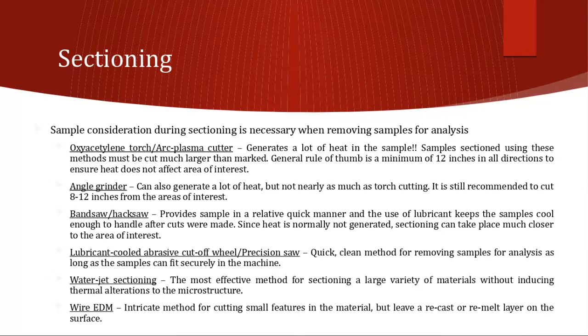If you don't have a bandsaw, then some of the other options you have, and this is something that you will be working on in the labs, are the lubricant cooled abrasive cutoff wheels and/or precision saws. The lubricant abrasive cutoff wheel is very clean compared to a hacksaw or bandsaw cut. It's a super smooth surface, with a minimal amount of surface damage compared to the bandsaw. Because it's quick, it's cool, it's clean, all you have to do is clean your sample after it comes out, and you're ready to mount the sample immediately after you're done.